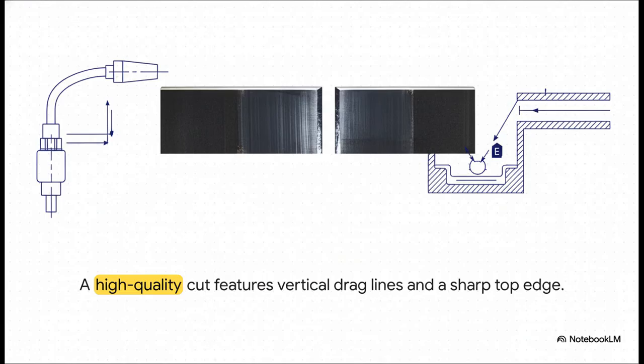And this is the goal. This is what a high-quality cut looks like, and every feature you see here is proof of a process that was perfectly under control. Take a look at those drag lines. See how they're almost perfectly vertical? And notice that sharp, square top edge with no melting or rollover. Getting a cut this clean tells you that the travel speed, the torch height, the gas pressures, everything was dialed in just right.